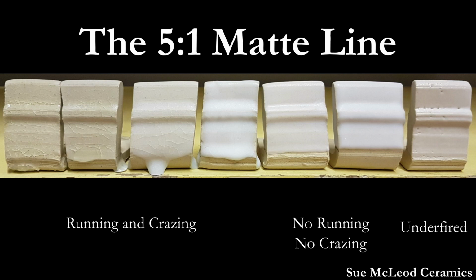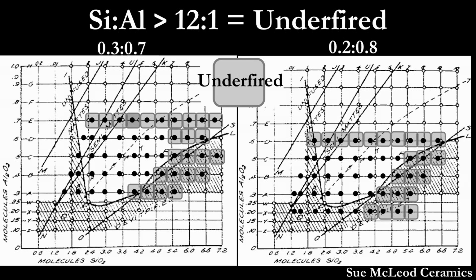As we move up the diagonal 5:1 line, increasing the silica and alumina proportionately, a couple things happen. The crazing is reduced until there is no crazing, and the running is reduced until there is no running. If we keep moving up the line, eventually the glaze dries up as it has too much silica and alumina to melt at cone 6. The results also show that there is a limit to how much silica and alumina a glaze can contain and still melt at a specific temperature, with a specific flux ratio and a set boron level.